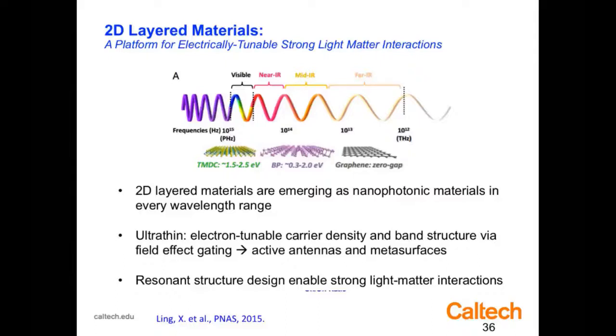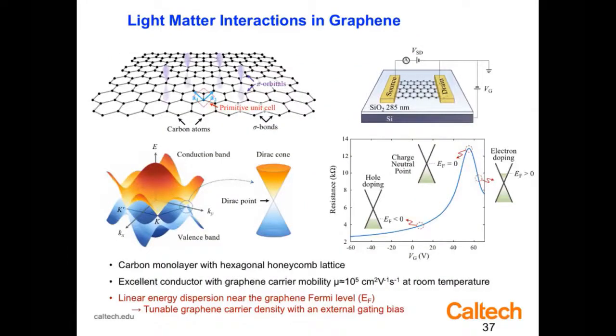And so I'll spend a little bit of time talking about graphene and mention that graphene has this characteristic feature of this hexagonal honeycomb lattice that gives rise to an unusual electronic dispersion. It's a linear dispersion, not parabolic like most semiconductors are. But because it's one layer thick, if I make a gated structure like I did for the indium tin oxide structures, I can change electrically the chemical potential for the electrons. I can dope graphene either p-type or n-type simply by changing the potential on the gate.